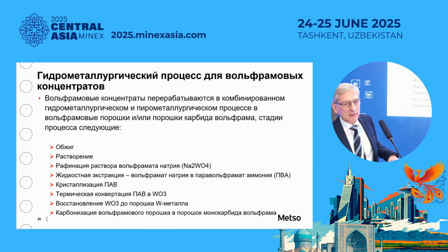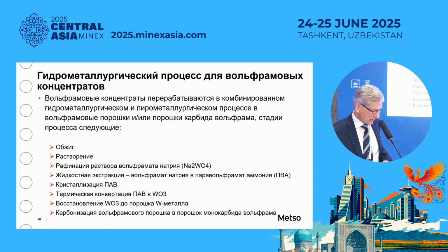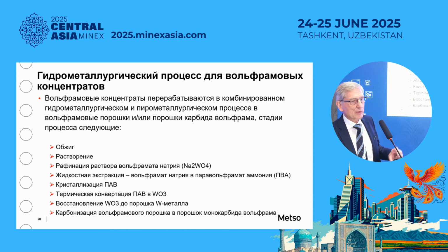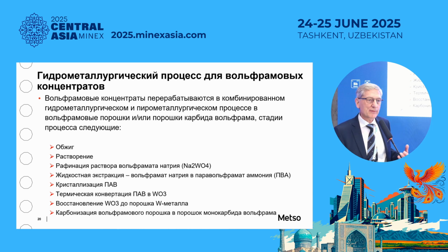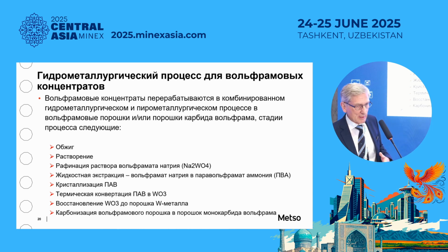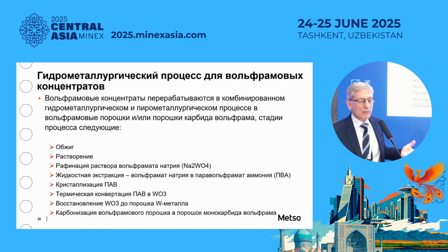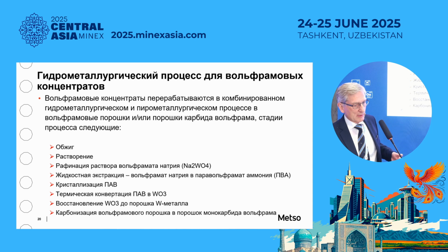From APT, we do a heat treatment to transform ammonium paratungstate into tungsten oxide. Then we do reduction of the tungsten powder from WO3 to tungsten metal powder, and then by heat treatment carburation we create tungsten carbide powder.